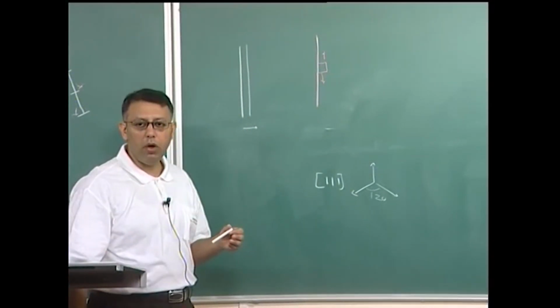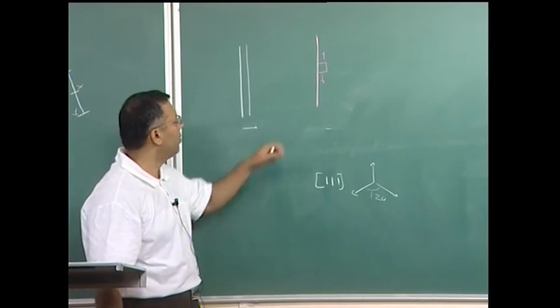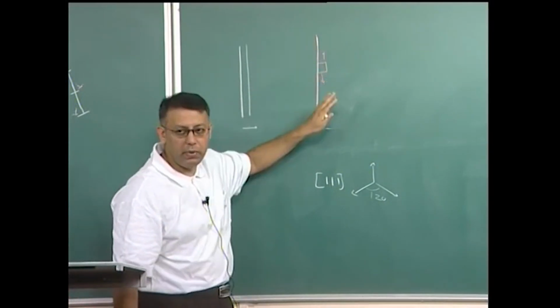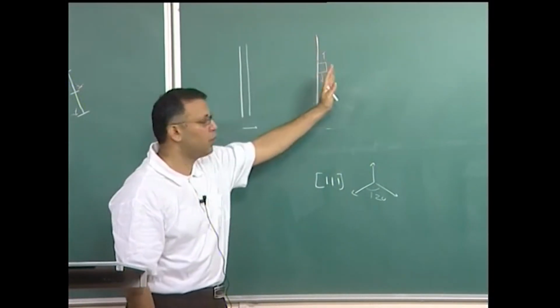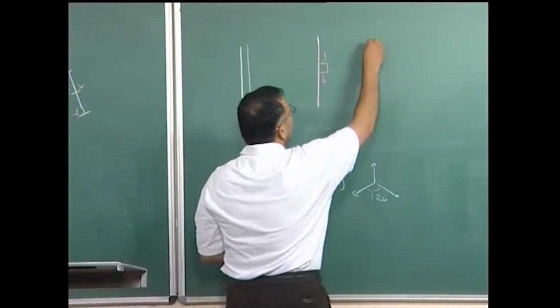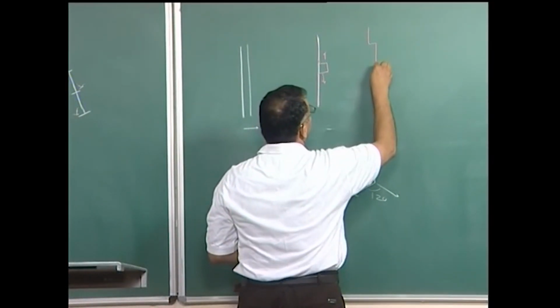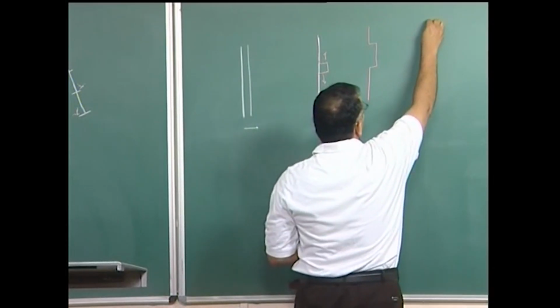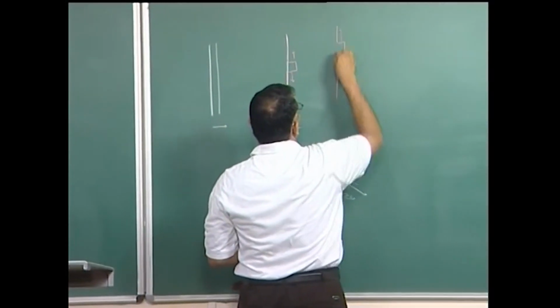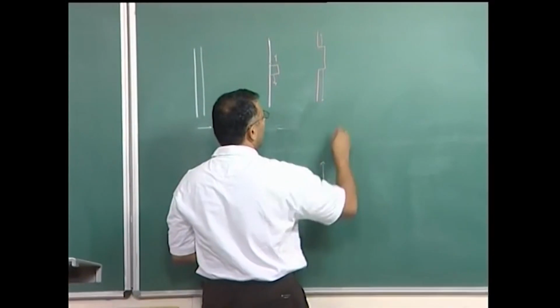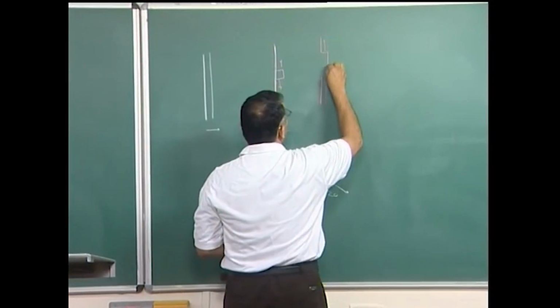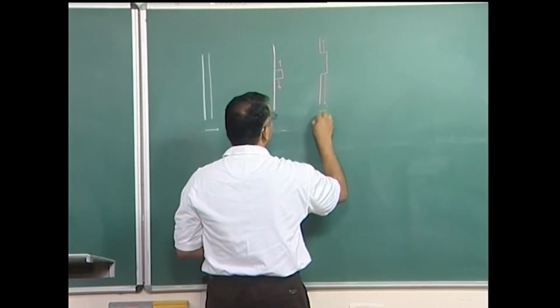That means, now the stress I need to apply is much smaller, because I am only propagating a small segment. I am not propagating the entire dislocation by one Burgers vector. So, this can actually propagate. And finally, of course, when the entire segment has left to the top, and this segment comes down to the bottom, I would have the motion of the dislocation stepped up by 1b.